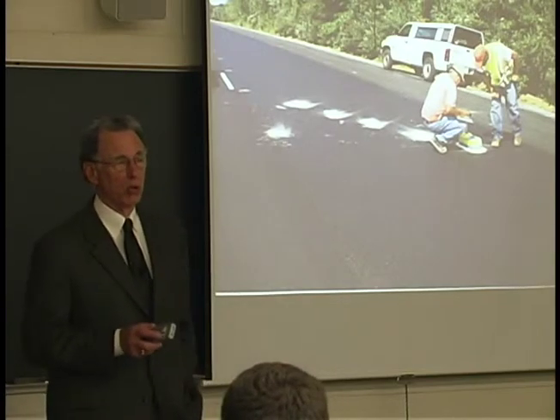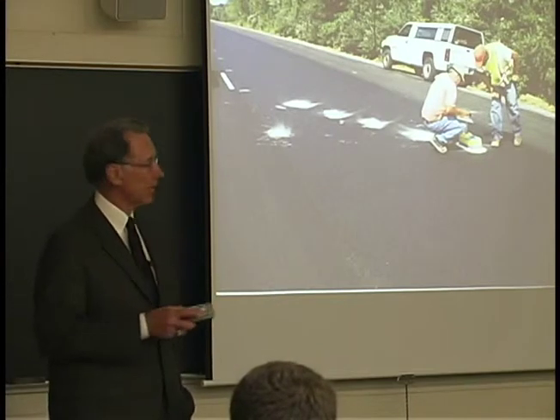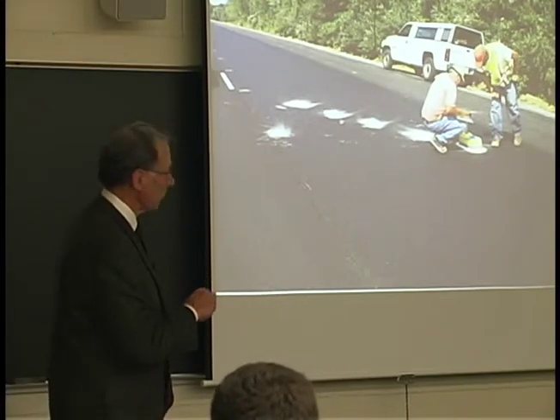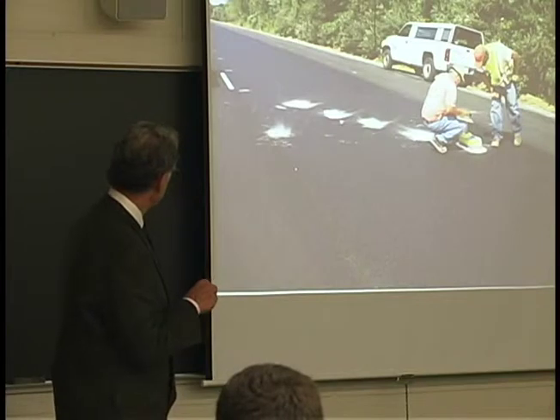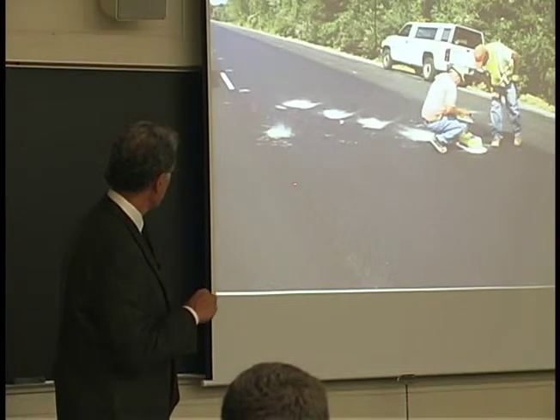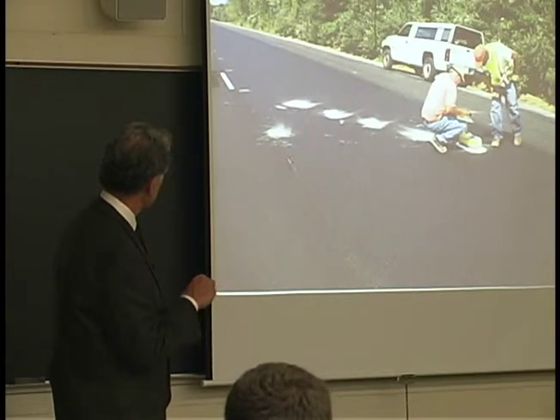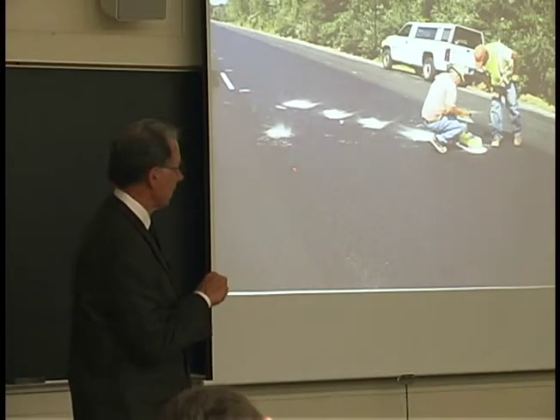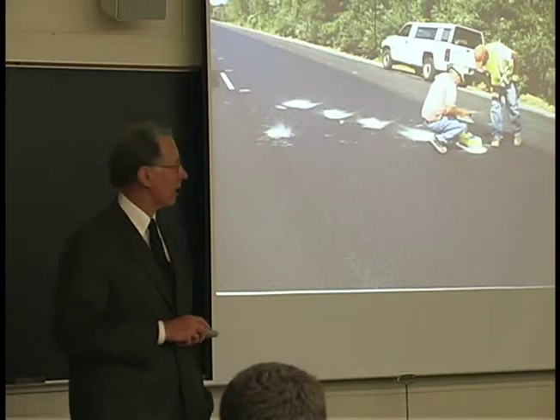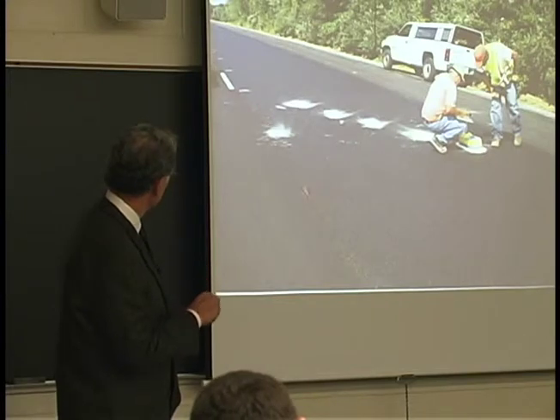If you drive down a roadway and you see problems with a pavement, whether it's asphalt or concrete, probably initially it's going to be right on the center line. Watch that if you have an opportunity, and if you start seeing the spalling here in the concrete or pieces of asphalt breaking out, it means that this probably was not consolidated well enough during the time of construction. Water begins to get down in here, and then it starts breaking from the bottom up. And so it's very, very important that you know what the densities are across that mat.